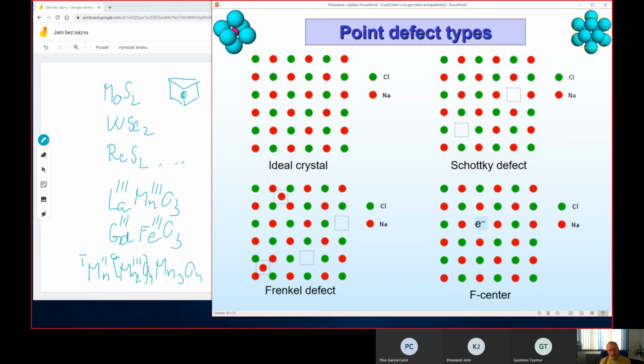In charged structures, there must always be a charge compensation, and I will talk about this in the last presentation devoted to electronic structure or band structure. Sometimes a charge defect can be compensated by electrons or holes in a given band structure, but sometimes the electron or hole is associated with a certain site, and in that case we speak about an ion of different valency.